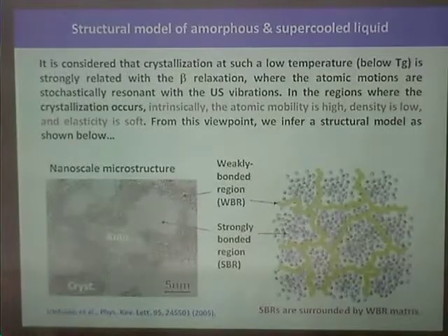Just as a simple suggestion, have you considered doing the same experiment but stopping it after 5 hours or 2 hours? That would give you an idea of nucleation, and you could decouple the nucleation from the growth. Yes, to see how this is. Okay, so it's a very good idea.